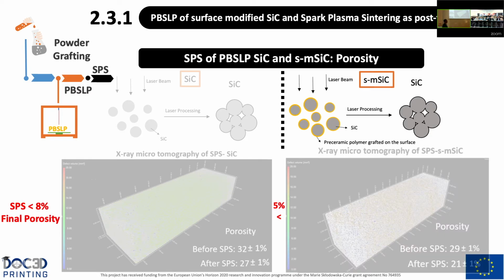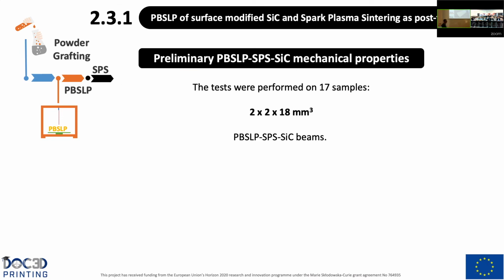So actually, comparing the surface modified silicon carbide and silicon carbide, there is a 5% difference of porosity, a similar value to that we obtained before. And actually with spark plasma sintering, we are able to decrease up to 8% the final porosity of the sample. Remember, we can treat complex cells of silicon carbide.